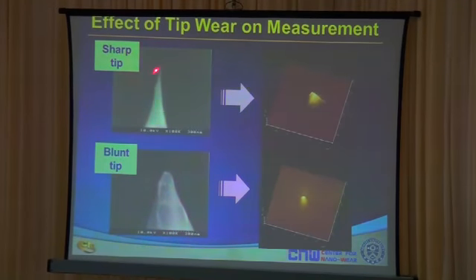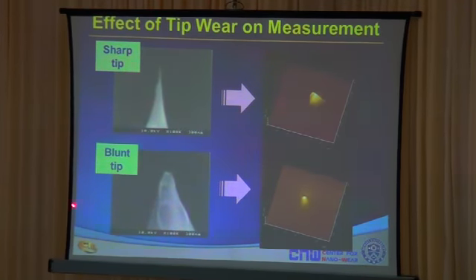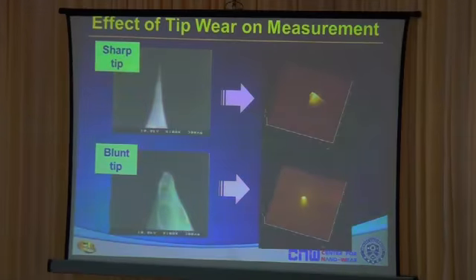So we've looked at how the sharp AFM tip wears. Now, if you had a feature like this on your specimen, and you use a sharp tip, you will have this feature represented very accurately. However, if you use a blunt tip that's been worn out due to contact, this particular feature will look like that. Therefore, it is of great advantage to use a sharp tip when you want to make good measurements using your AFM. Many times, users don't realize that they just use the same tip to measure the surface because of convenience. And these tips are expensive, so you don't want to replace them every time. But you have to be aware that tips do wear out and it will affect your measurement significantly.